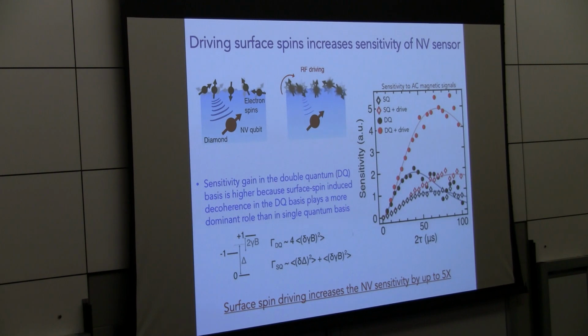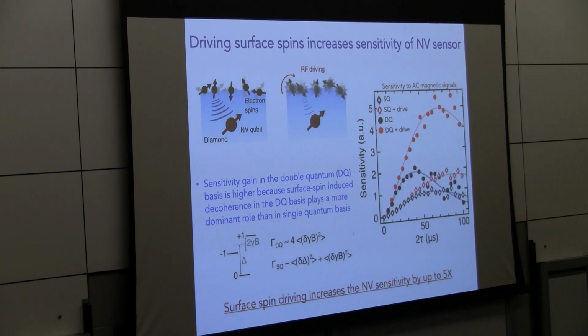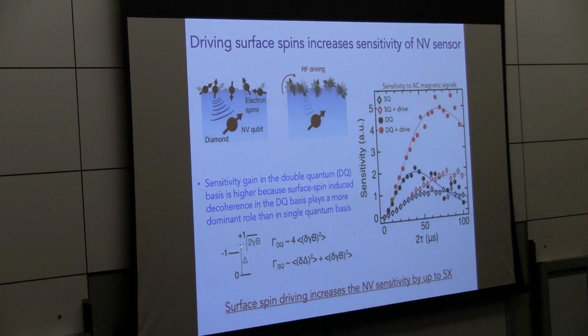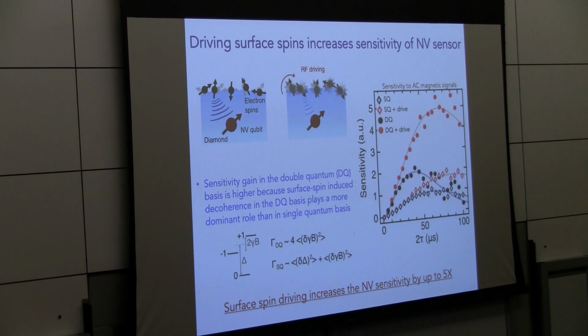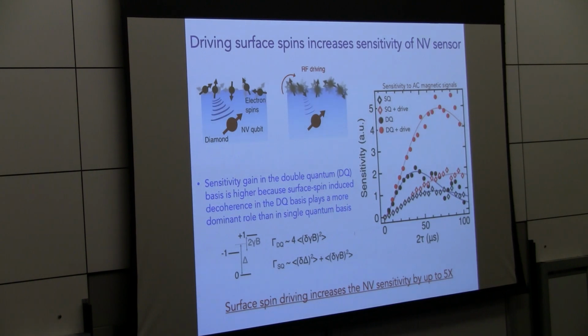Quantitatively, we measured the enhancement in the sensitivity of the NV center in the presence of driving the surface spins, and see that we get up to a factor of 5 enhancement in sensitivity, in particular when we use the plus and minus 1 qubit as our sensor. The reason is pretty simple to see. If I use this qubit basis, the minus 1 and plus 1 is doubly sensitive to magnetic fields. So that makes a great sensor, but it's also doubly sensitive to those fluctuating spins at the surface. But if I can remove the effect of those fluctuating spins, then I can have an overall higher enhancement in my sensitivity.